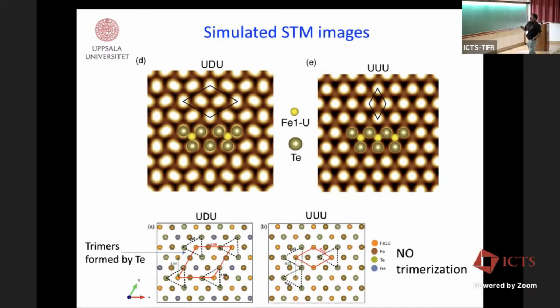This oblate structure appears because when you have a UDU structure, one of the iron atoms is missing there, and that's why the tellurium atoms come closer and make a trimer. This trimerization is the reason why these white-shaped objects are not really circular there. They are oblate, whereas in the UUU, no such thing happens, no trimerization, and everything looks pretty symmetric.